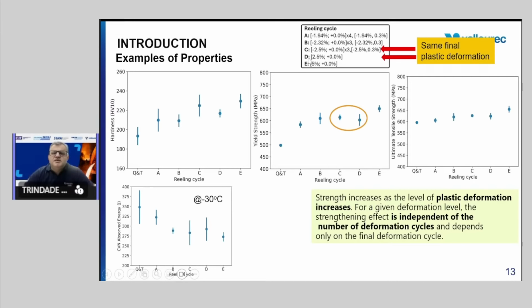But what we can see is that at the end of C, we are going to have around 2.5% remaining plastic deformation, and D also 2.5%. Independent of whether it is monotonic or cyclic, we have at the end similar or the same behavior. This is a very important conclusion for the industry. If we want to simulate the cycle of the reel drum, if we do monotonic simulation or cyclic simulation, it seems to be the same behavior. What matters is not the number of cycles, but the final plastic deformation that remains in the pipe.